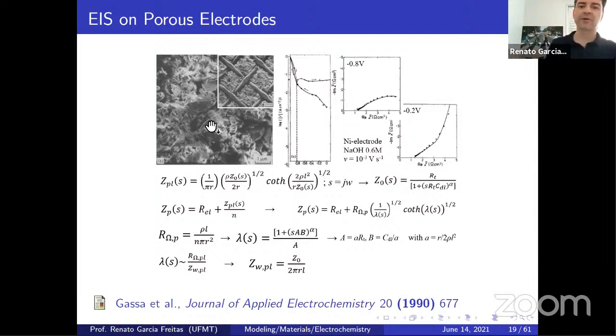So Gassa was the first to separate the contribution of the pore resistance and the surface resistance as well, because we have here ZPL. ZPL is the impedance of a single cylindrical pore, like that one, which has a dependence on the hyperbolic cotangent. Z0 is the specific impedance per unit area, the parallel impedance for a capacitor like that, isn't it? We have the resistance in parallel with a capacitor.